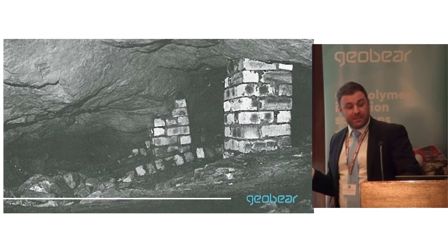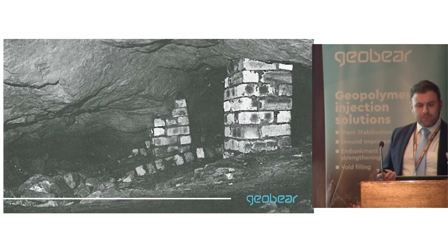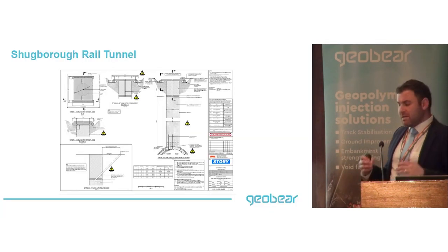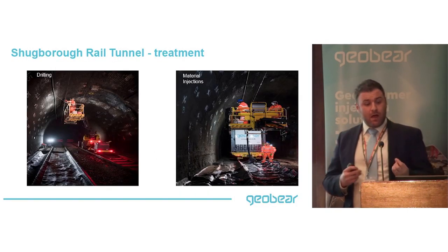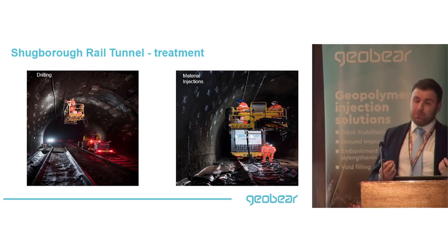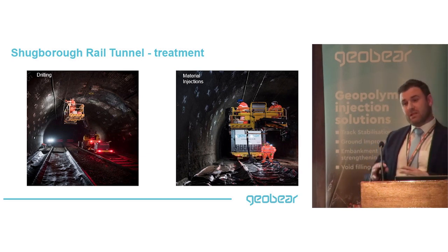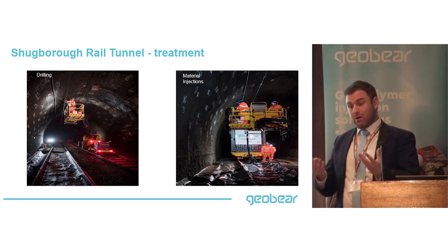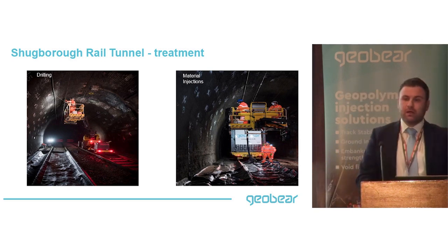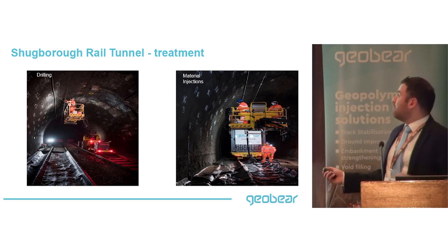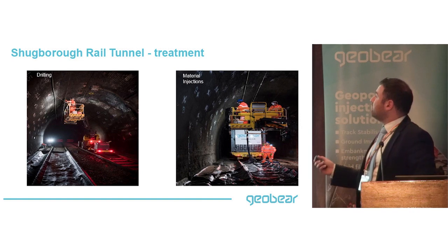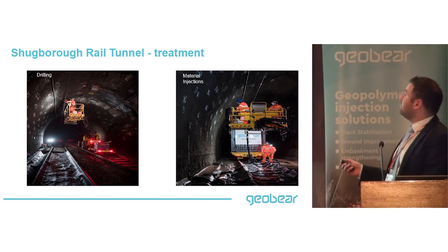So what we've done on this particular scheme is basically used a high density geopolymer, very strong, but at the same time quite light compared to what you would get from conventional grouting. We basically drilled every meter center in a staggered pattern and injected the geopolymer.